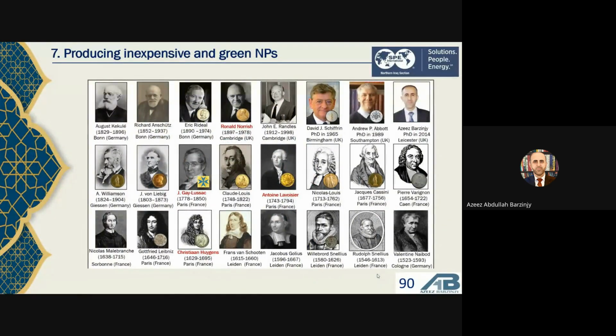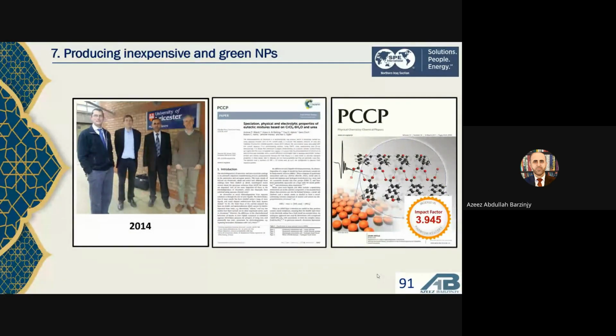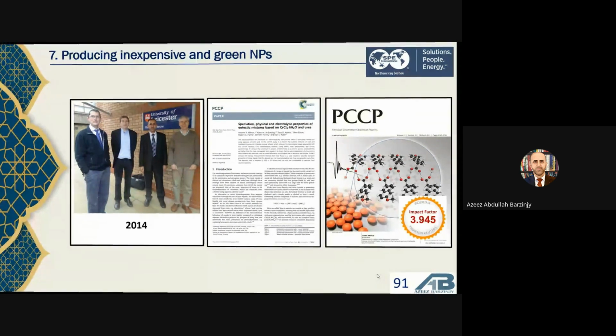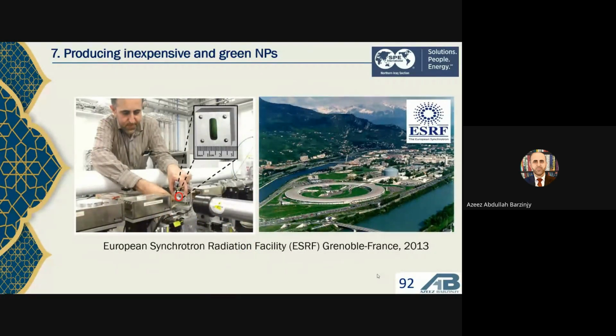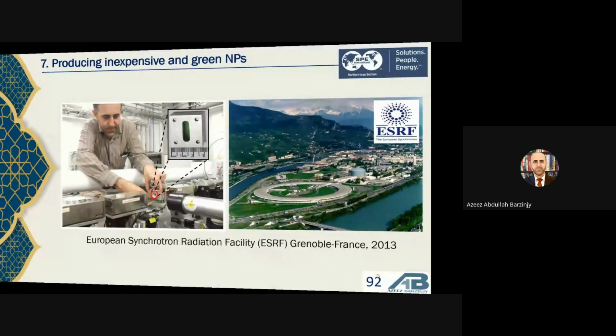And I was lucky because I was working with Professor Abbott during my PhD time. And you can see here, Professor Abbott has a huge, very strong profile. And this profile dates back to great scientists such as Gay-Lussac and Lavoisier and Christiaan Huygens and so on. So this is me when I produced the first chromium nanoparticle from ionic liquid. This chromium nanoparticle can be used as an anti-corrosion. And then we utilized this chromium solution in order to find the distance between the atoms and also the number of the atoms. And we did this in the European Synchrotron Radiation Facility in Grenoble, France in 2013.